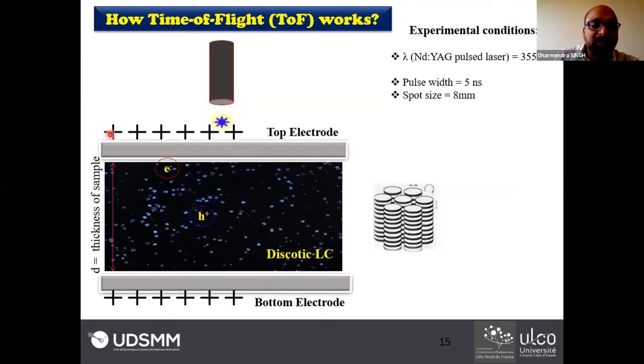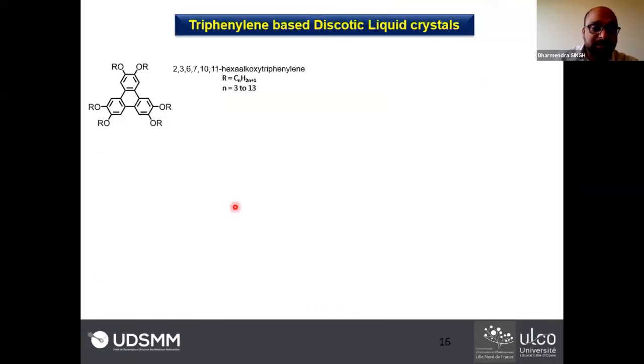What happens if we apply a negative voltage? It will compel electrons to go. So by recording the electron photocurrent curve or the hole photocurrent curve, we can estimate the electron and hole mobility separately. This is a fantastic technique, because we can even detect ionic impurities, since the mobility of ionic charge carriers is much lower than that of electronic charge carriers. So the transient peak will be at another place. We can estimate whether the charge transport is associated with electronic charges or is due to ionic charges. We have investigated some systems.